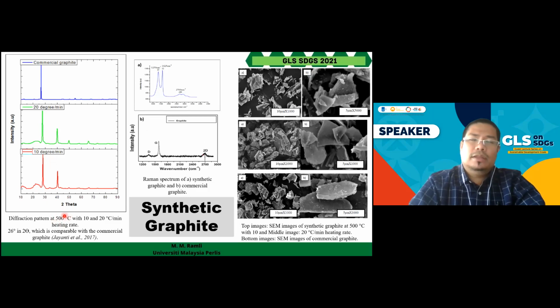If you look at the literature, there is a lot of synthetic graphite being produced from biomass waste. Most of the production basically applies a high temperature. So what we are trying to do here is lower the temperature, and we managed to get it at 500 degrees C with 10 and 20 degrees per minute in terms of the heating rate.